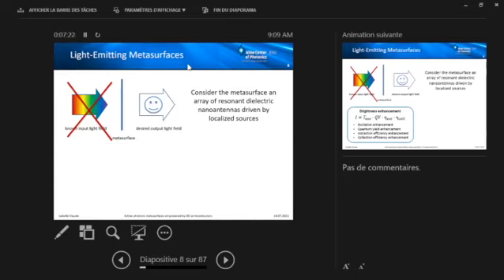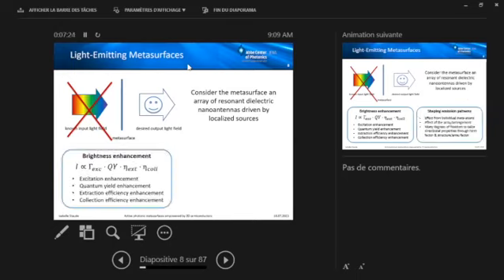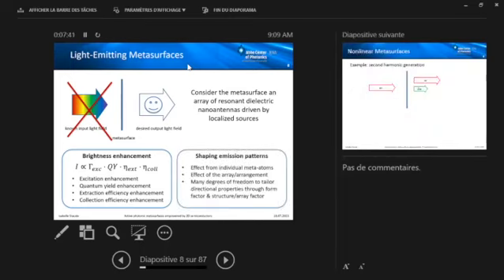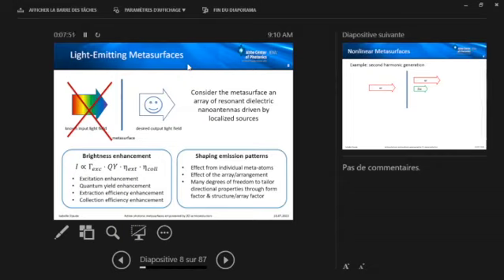And what can it help us? So basically, there are two things that the metasurface can be good at. One is brightness enhancement through various mechanisms like excitation and quantum yield enhancement, but also extraction and collection efficiency enhancement, which is of course related to the spatial emission profile of the coupled system. And this is also a point by itself that the metasurface is very good at shaping emission patterns, because we can combine the effect of the individual meta-atoms, which can already be a directional nanoantenna, with the effect of the array or arrangement. So we get many degrees of freedom to tailor the directional properties.